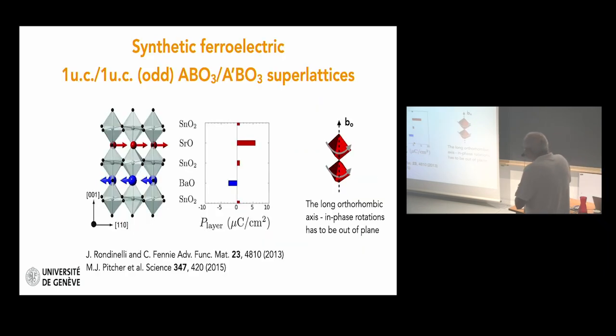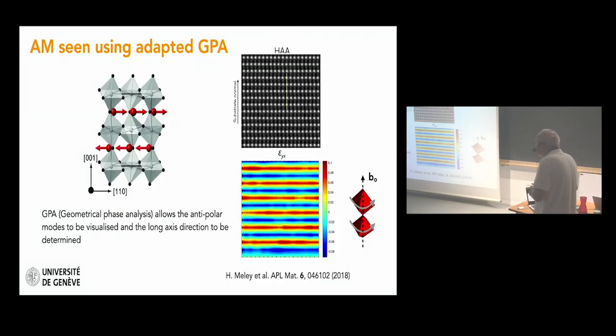one unit cell, you see that now in this structure, where you have strontium here and barium here, so it's strontium TiO3, barium TiO3, you see that you will have a displacement of the cations in this direction, the strontium, but the next plane is barium. The displacement will be different, the Born effective charge will be different, and eventually you develop a net polarization. And there has been some work in this direction. And I will mention a little later in the talk that it can be interesting to measure this